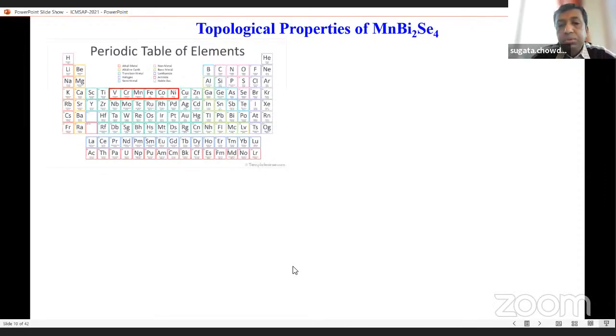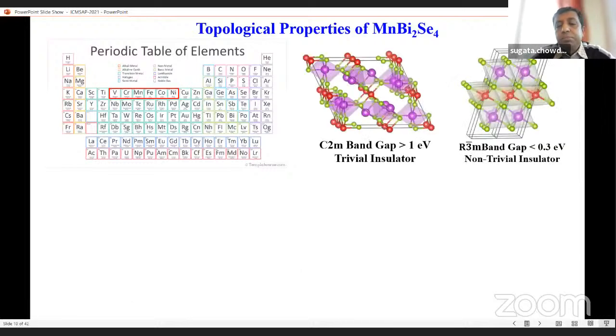So first we look at the periodic table. Vanadium, chromium, manganese, iron, cobalt, and nickel are all magnetic. But interestingly, manganese chemistry and the hybridization process created the opportunity to develop a topological insulator. The manganese bismuth selenide structure has two different symmetries: one is C2/m, another is R3m rhombohedral structure. It is known that the C2/m symmetry is a trivial insulator, and the R3m symmetry is a non-trivial insulator.